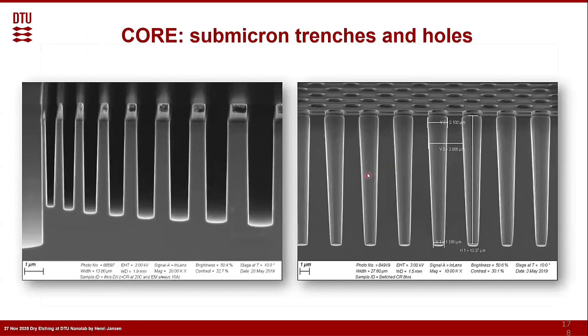And you can see that if you do so, it's totally fine. So you have structures which are just like the Bosch process. They are straight, a little bit positive tapered here, and nothing different. But the only exception is that this one is tool friendly. So that means very reproducible and reliable. The etch rates, though, are much lower. So typically you will not reach, let's say, 20 microns per minute, but that's a different subject.